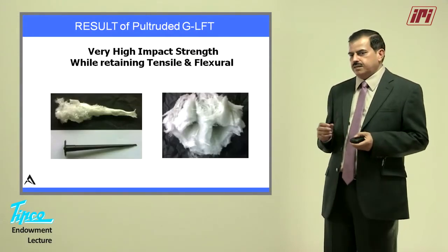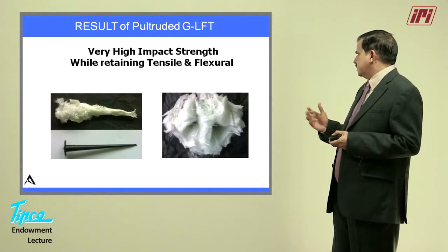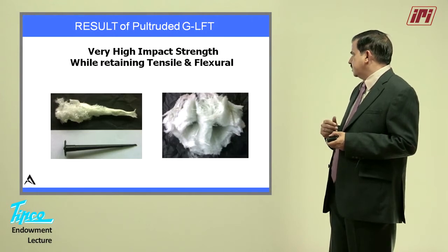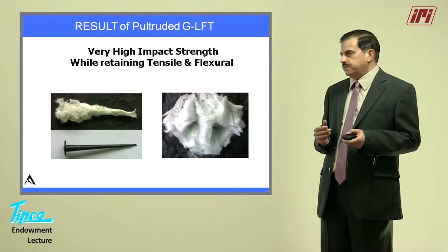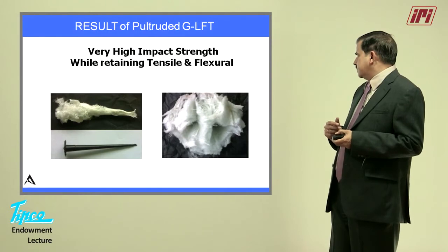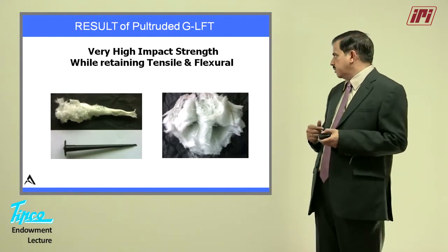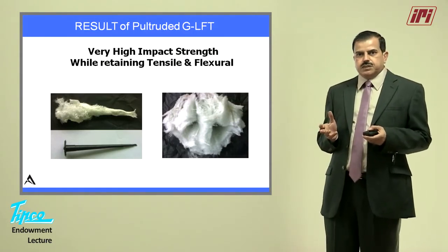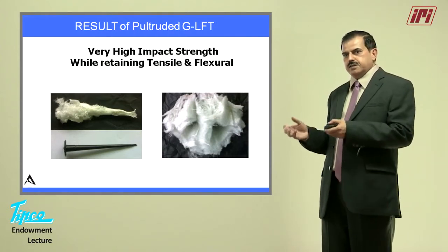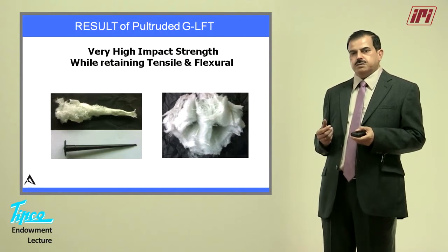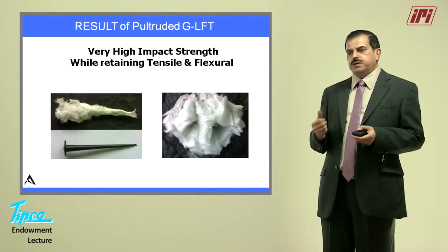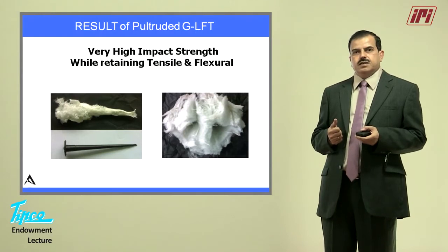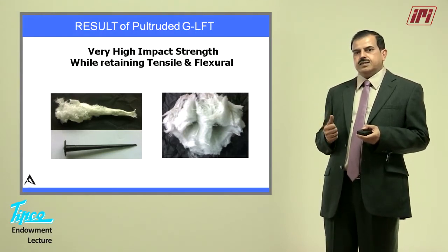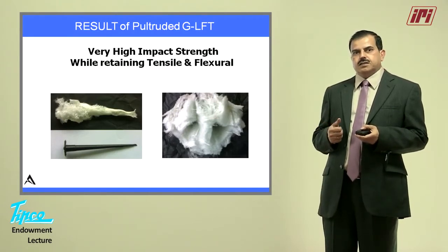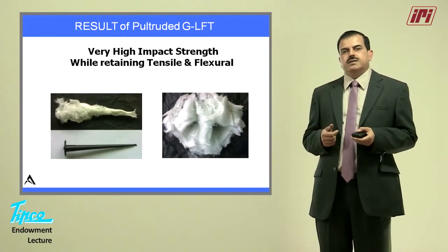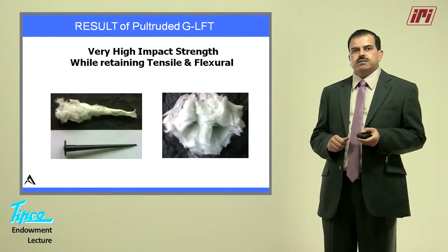I would like to spend some time on this slide. This is one of the best ways to find out whether your component is made up of long glass fiber or short glass fiber. And this also gives an idea why the impact strength has become so high while using long glass fiber. Basically, if you make a component with short glass fiber and the same with long glass fiber, take out both the components from the mold and put these two components in the furnace at around 650 degrees centigrade. You will see a big difference. In a short glass fiber filled PP compound or PA compound, the polymer will burn off at 650 degrees centigrade if you keep it for half an hour, and all the glass fibers you will find flat on the surface.